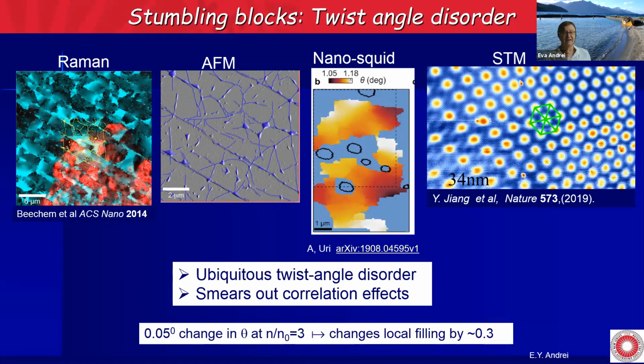So, for example, a twist angle change of about 0.05 degrees at a filling of 3 changes the local filling by 0.3, which means that twist angle disorder is really a big problem, especially if you want superconductivity. Unless you have a percolating path across the sample, which is exactly at the magic angle, you're not going to see superconductivity.